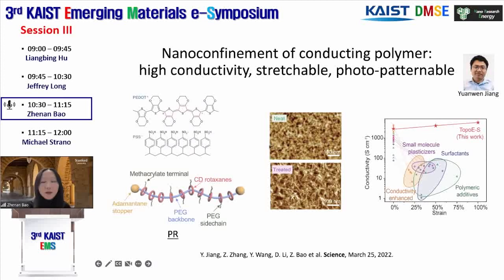And going from semiconducting material to conductive material, this nano-confinement effect again allowed us to incorporate multiple functionalities, such as high conductivity. This is a result of the nano-confined structure. And then the addition of stretchability as well as photo-patterning capability. And this is realized by designing a single additive, which acts as a photo-initiated cross-linker, but also has the polar PEG backbone that's used to induce the nano-confined structure, because this polar component can alter the interaction between the PEDOT and the stabilizing PSS and induce the nano-confined structure.